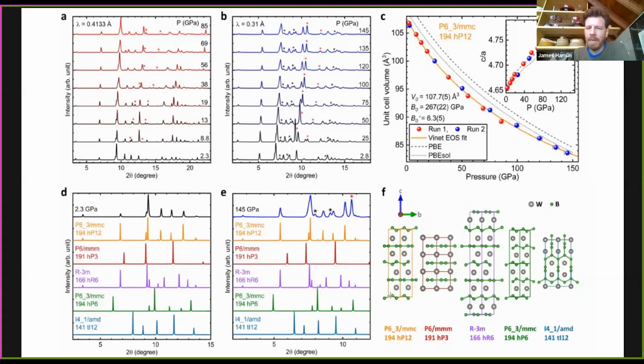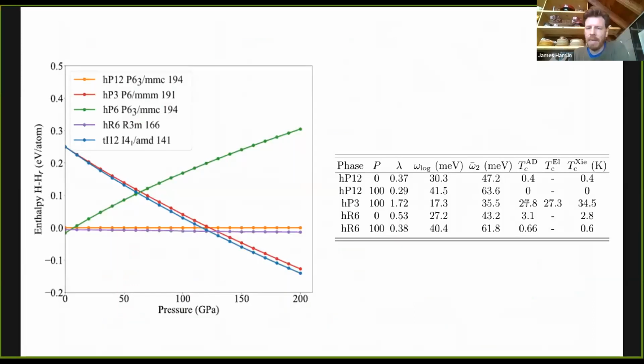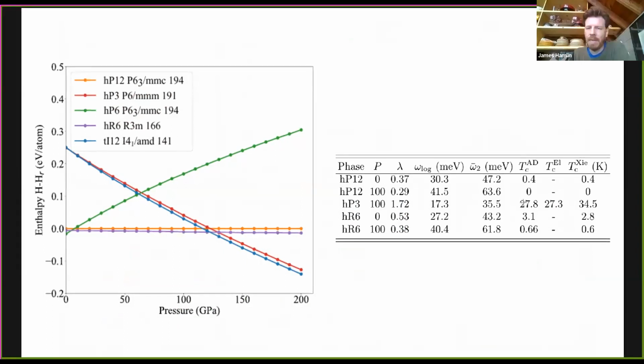So why then is superconductivity appearing? Well, our collaborators, Vinkia and other members of our team, worked on predicting TC for the various different structures that appear. And in fact, the only one that seemed to show a significant TC was this HP3 MgB2-like phase. All of the others showed very low critical temperatures. The HP3 phase supposedly becomes stable above 120 GPa, but again, it seems like a similar situation where without heat, we were unable to convert the sample fully to this more stable phase.